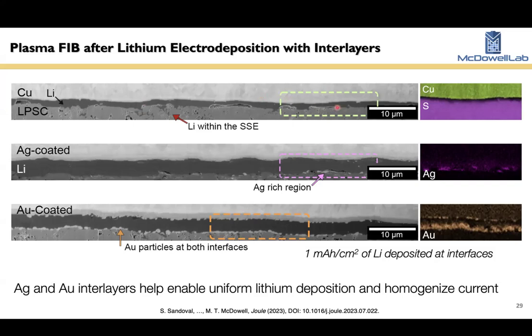So with bare copper, the lithium region is shown here. These are plasma FIB images. So we've cut into the cells after extracting them, after depositing lithium. You can see that the lithium, this darker region, is quite non-uniform. There are pores and voids present at the interface, and some of the lithium has actually grown into the solid electrolyte pores. So this is preparing to short circuit, basically. When we have silver-coated copper, the lithium is much more uniform overall. That's important. There's also some evidence of silver present. Silver partially dissolves into the lithium because it forms a solid solution.